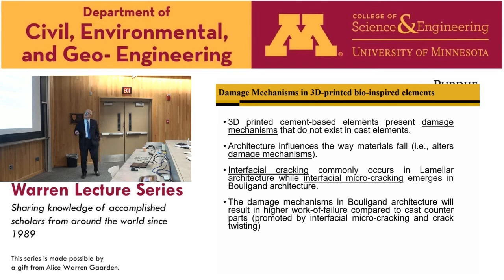The damage mechanism that exists in those 3D printed elements is different than the damage mechanism that is present in the cast element. And particularly the internal architecture influences the way the materials fail because we are altering the damage mechanisms. And not surprisingly, you have micro-cracking at the interfaces, but rather than viewing it as a bad thing, you have a weak interface, and by changing the orientation of those weak planes, we're taking advantage of it, trying to redistribute the cracks throughout the microstructure. If we redistribute the cracks, we'll have a higher work of failure compared to the cast counterparts, or specimens that were just created using the regular casting process.